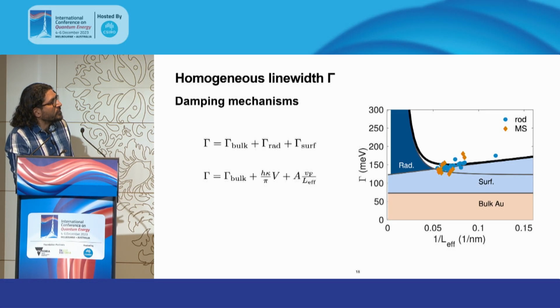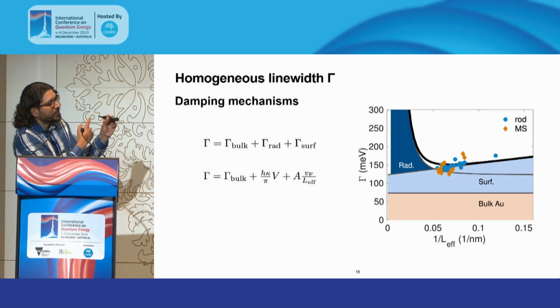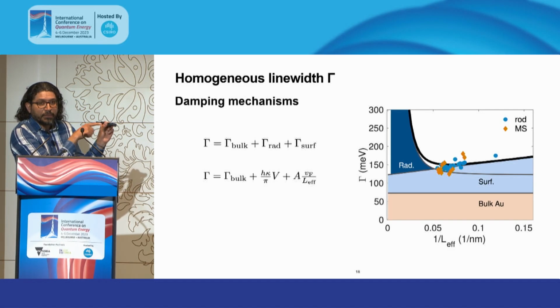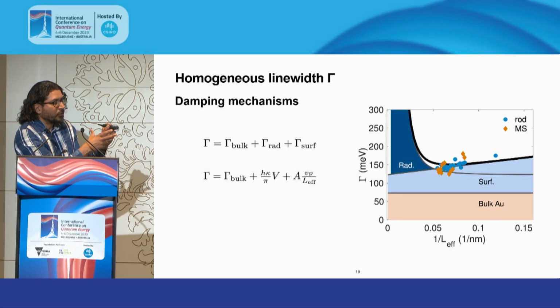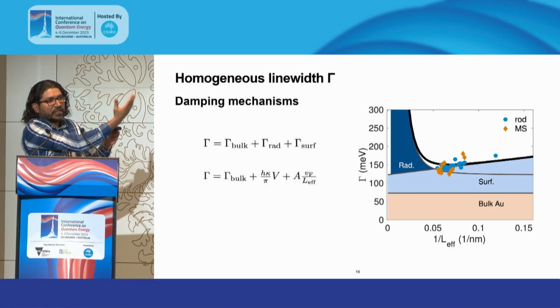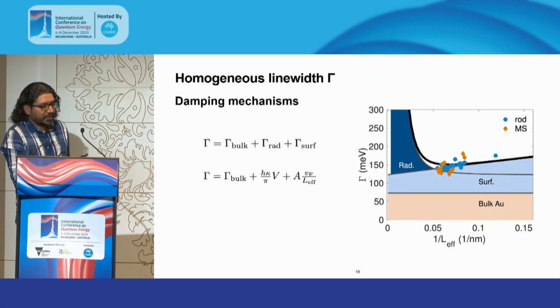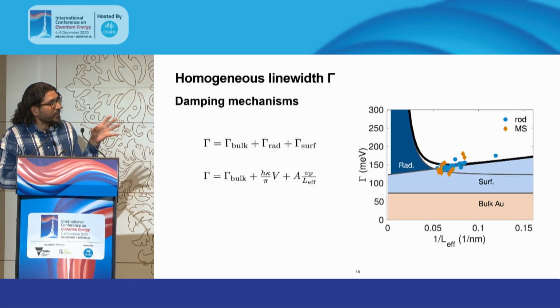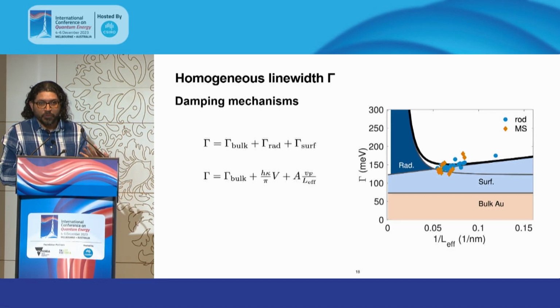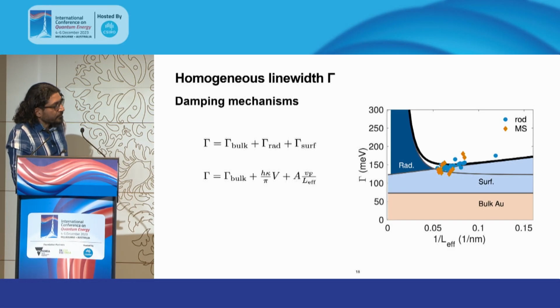The second contribution is due to radiation damping. As I said before, for the nanorod, there is a longitudinal dipole plasma oscillation. This has a strong dipole moment, and as a consequence of that dipole, there will be a lot of radiation scattering from the particles. This radiative damping is what leads to the beautiful colors of metal nanoparticles. This radiative damping is proportional to the volume V of the particle. So larger particles would have a strong radiative damping.